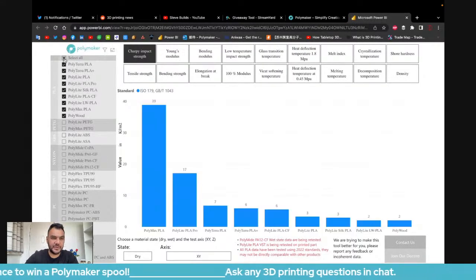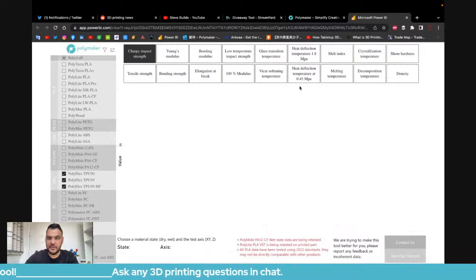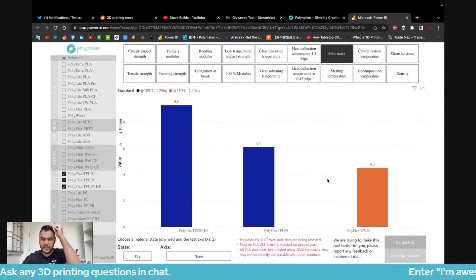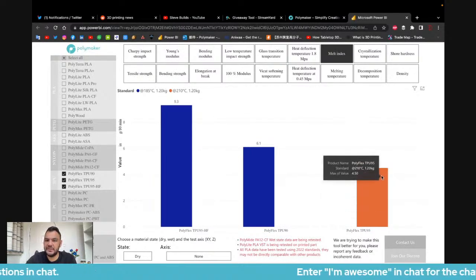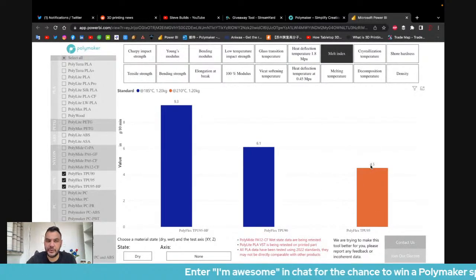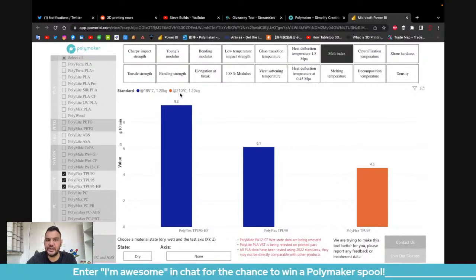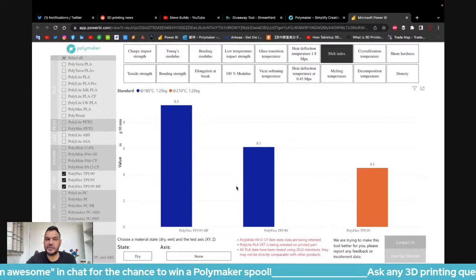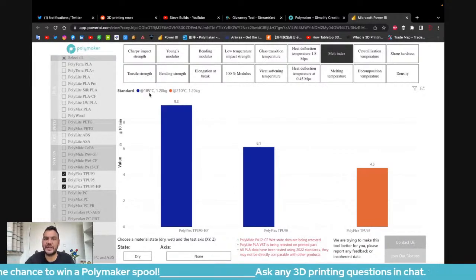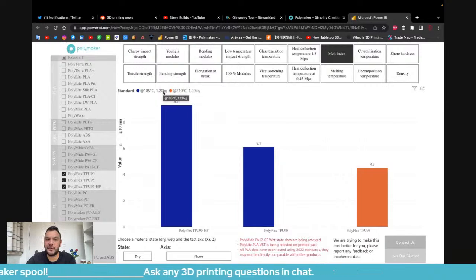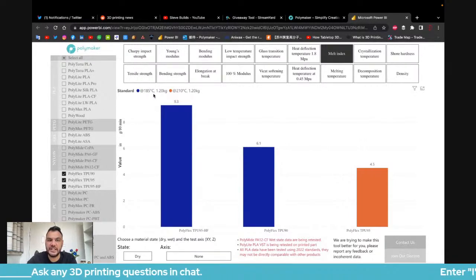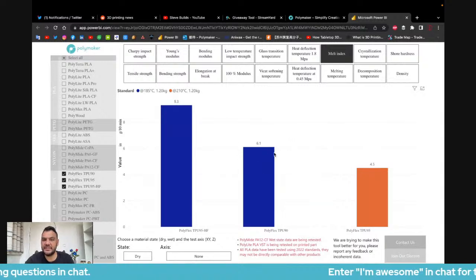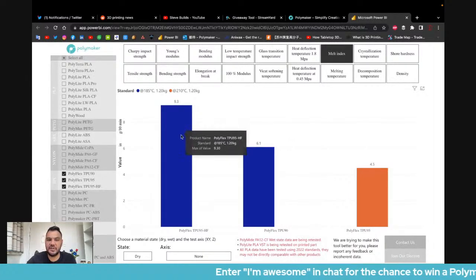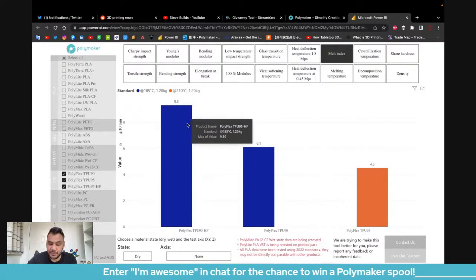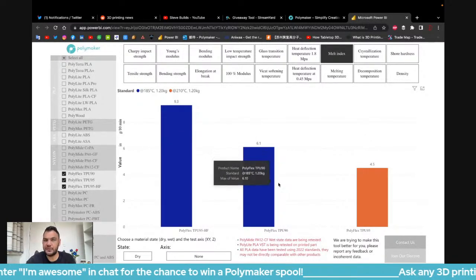And then if you go and check the melt index of both TPUs, you can see our regular TPU95 is 4.5 grams per 10 minutes, and that was tested at 210. And these ones are so high flow that we had to test them at 185 degrees. For the same amount of force, but 25 degrees less, it's producing TPU90 at 6.1 grams per 10 minutes, and TPU95 HF at 9.3 grams per 10 minutes. So these are really high flow TPUs.